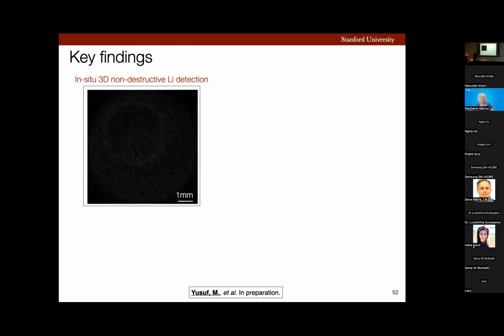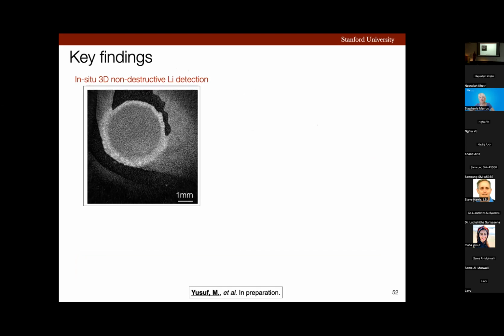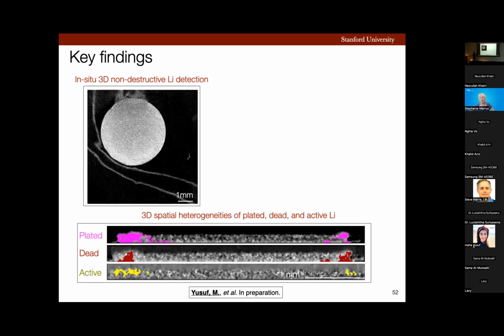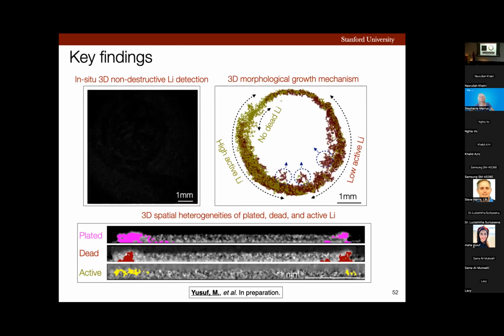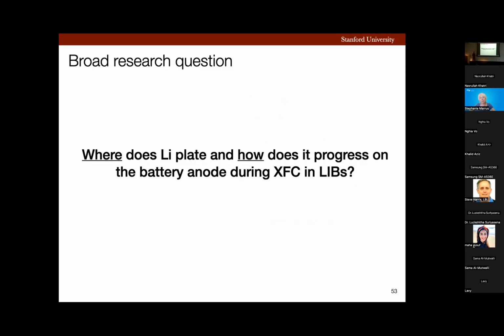Thus, to summarize, in this work, I have conducted in situ 3D non-destructive detection of lithium plating on graphite in a full cell battery. My work has shown 3D spatial heterogeneities in the behavior of plated, dead, and active lithium at 1C versus 6C. And simultaneously, the work also showed different morphological growth mechanisms of lithium plating and how they propagate under fast charging. Now, I hope with my work, I have convinced you that I answered where lithium plates and how it progresses on the battery anode during fast charging in lithium-ion batteries.